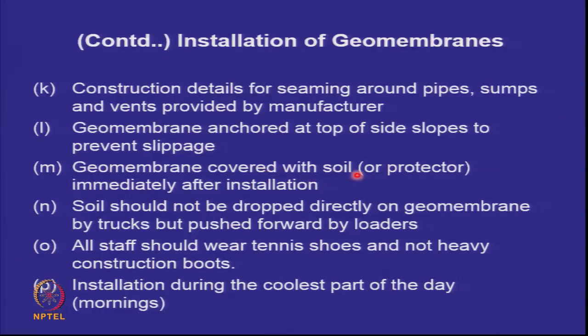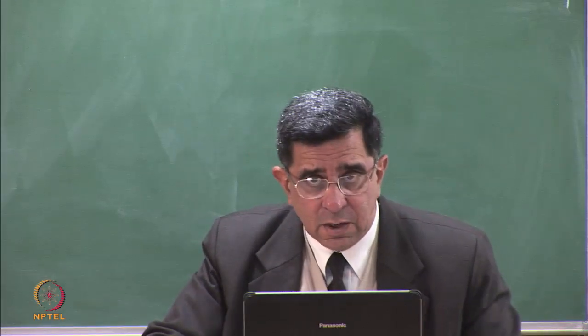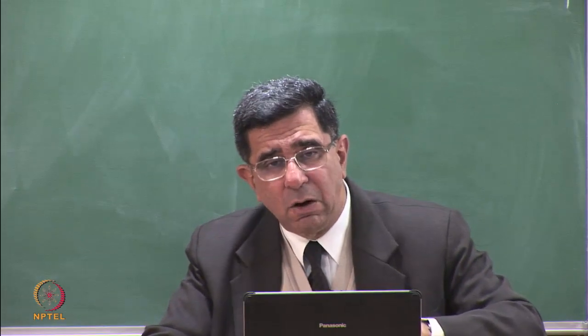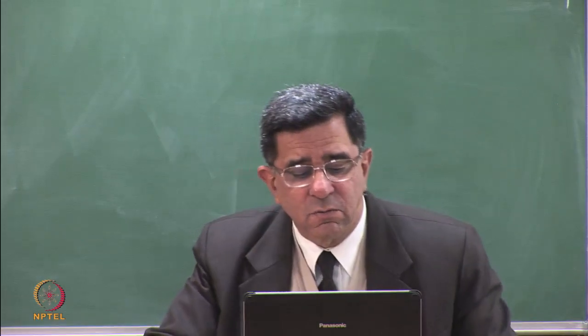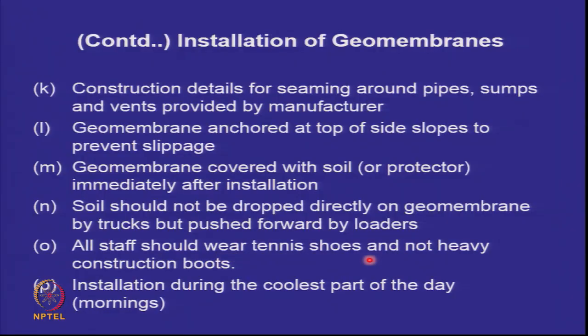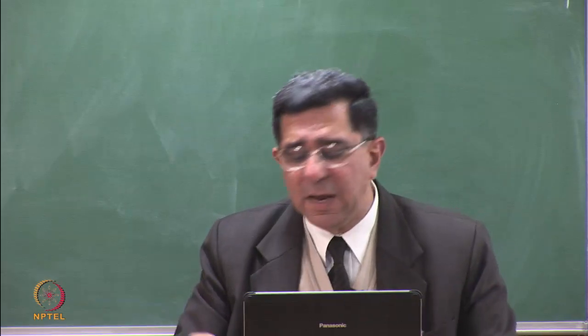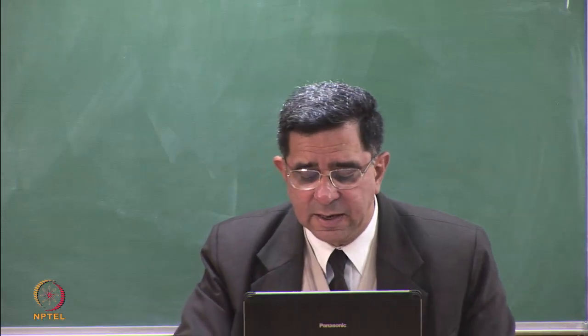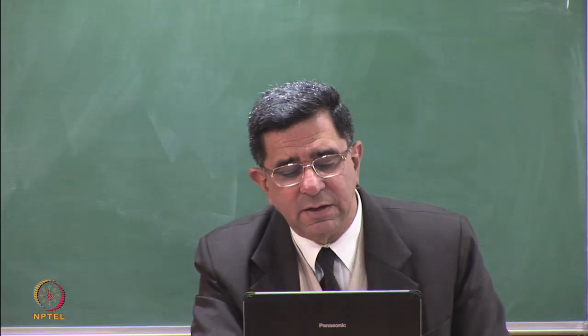Geomembranes should be covered with the soil or the protector immediately after installation. Soil should not be dropped directly onto the geomembrane, but pushed forward. In India, we do this manually, but in developed world, they use light crawler mounted loaders and they push this forward. All staff should wear tennis shoes and not heavy construction boots. Installation should be done during the coolest part of the day when the geomembrane has not expanded. Otherwise, there is a thermal expansion coefficient of the geomembrane and they can become longer during the daytime.